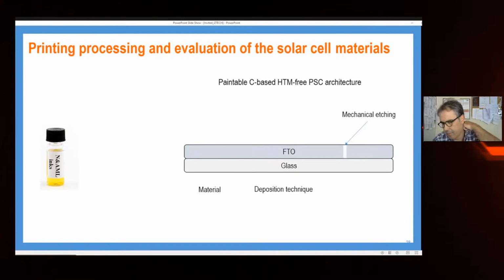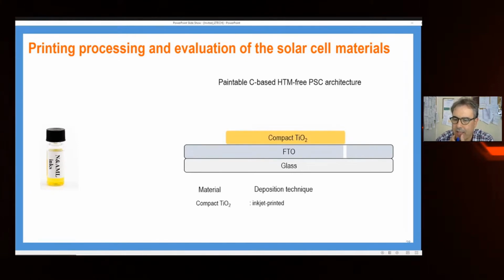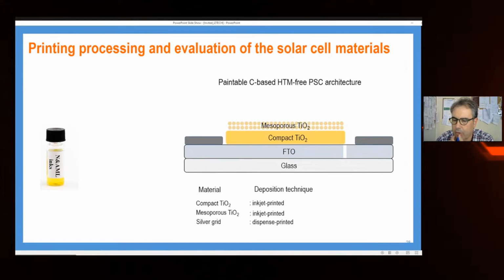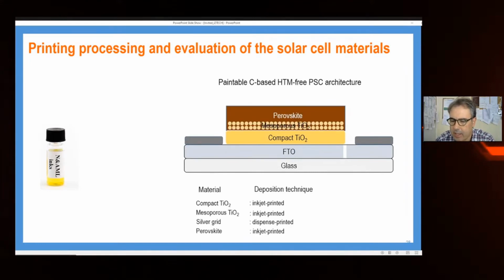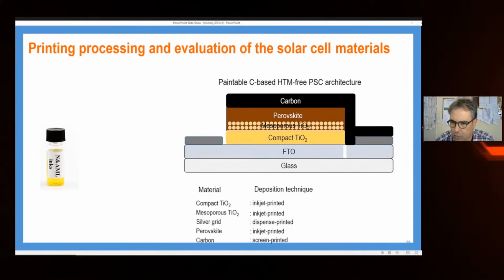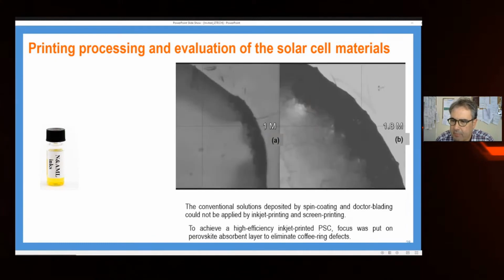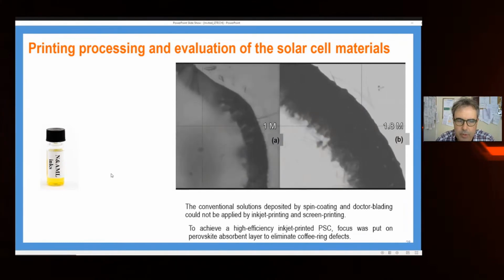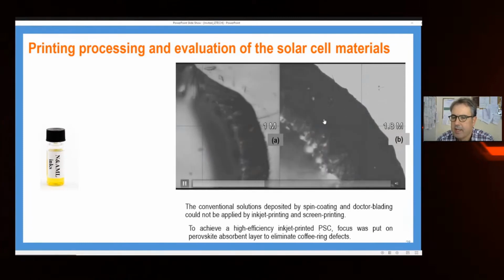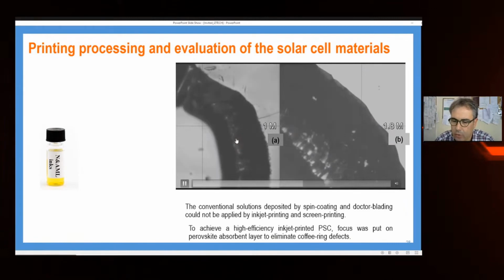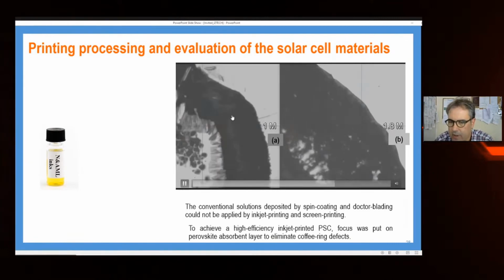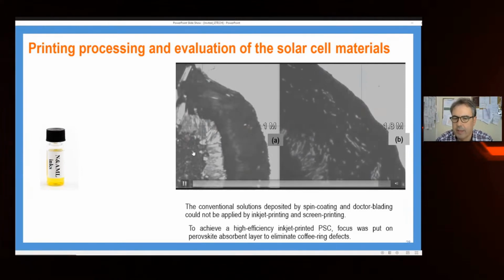This is the procedure that we follow to make the devices, the modules. Everything is, as you may see, inkjet printed on top. The only material that is screen printed is the carbon, which is viscous. It is very attractive, but as I said before, the problem with printing is that you have to develop special inks for this method, because the common problem that we face here is the ring effect, the coffee ring effect, which means that the crystallization of perovskite is better at the edges than in the middle of the material. That's why we need to play with inks to make very good inks for this kind of deposition method.